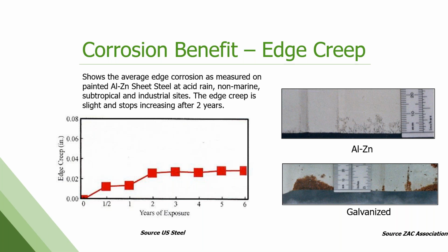And I mention that because we run into this in accelerated test as well. Accelerated corrosion testing doesn't always show the benefits of the aluminum zinc product. We really need to look at real world. You know, for 1,000 hours in a lab setting for corrosion, the galvanized will look better. But if you let that test run for 3, 4, 5 months, you would see that the aluminum zinc product slows down and stops corroding while the galvanized continues. So we're always a little hesitant if we get a request from architects or builders or specifiers to show the accelerated lab studies of these two products, because they don't really tell the tale.